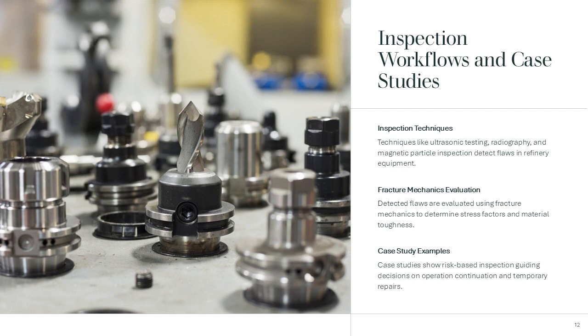For example, a pressure vessel with a detected surface crack was assessed using API 579 Part 9 procedures. Calculations showed that the stress intensity factor was below the material's fracture toughness, allowing continued operation until the next scheduled shutdown. Another case involved piping with multiple flaws where crack growth analysis guided the decision to implement temporary repairs. These examples highlight how fracture mechanics supports risk-based inspection strategies, optimizing resource allocation and ensuring safety.